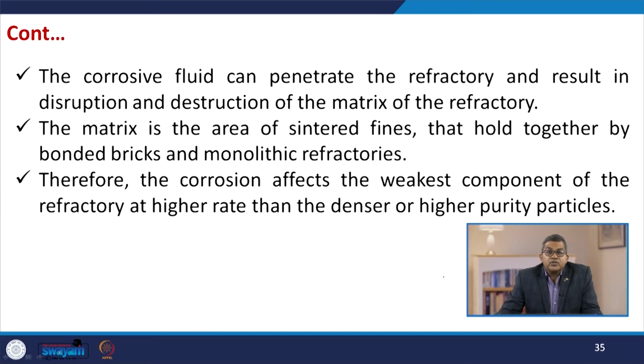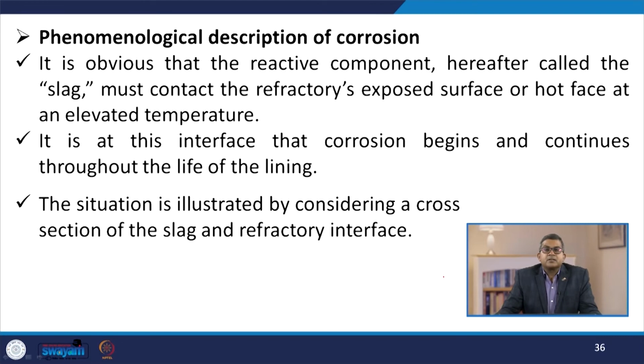Now, the corrosive fluids can penetrate the refractory and result in the disruption and destruction of the matrix of the refractory. Now, the matrix is the area of sintered fines that is held together by bonded bricks and monolithic refractories. Therefore, the corrosion affects the weakest component of the refractory at a higher rate than the denser or higher purity particles. Phenomenological description of corrosion.